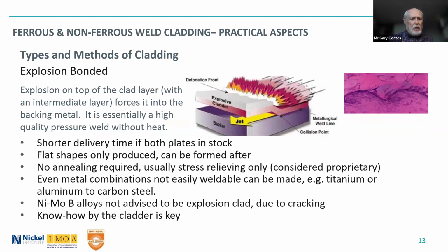The second major method is explosion bonded, and essentially you have your backing material on the bottom, you have a compound on top of that, and then you have your CRA layer on top of that, and then you put your explosive on top of that, and then you get a big bang explosion there, and that will do essentially a pressure weld into the two materials. And the cross section on the right there shows that if it's properly done, you get a really, really good bond there. So it is a very popular way of cladding.